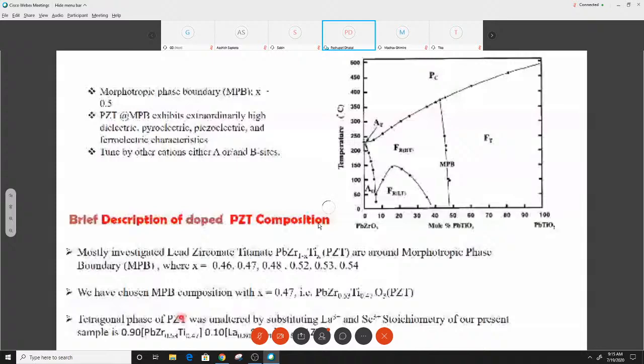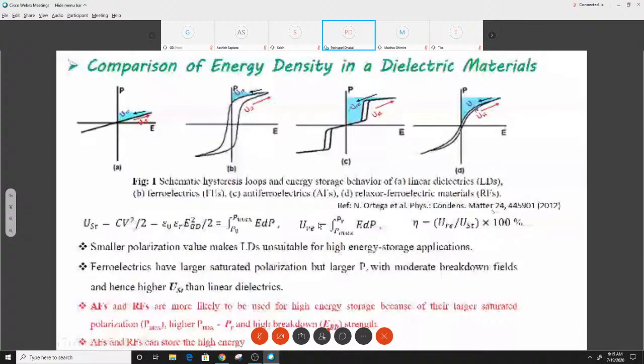This is the comparison of energy density in dielectric materials, that is, polarization versus the electric field. This is for the linear dielectric. This is for the ferroelectric material. This is the antiferroelectric, and this is the relaxor ferroelectric material. Basically, energy storage capacity can be calculated by CV squared by 2. So the higher the dielectric constant and breakdown strength, the higher the energy storage capacity. And in this figure, this shaded part gives the energy storage density of these materials.